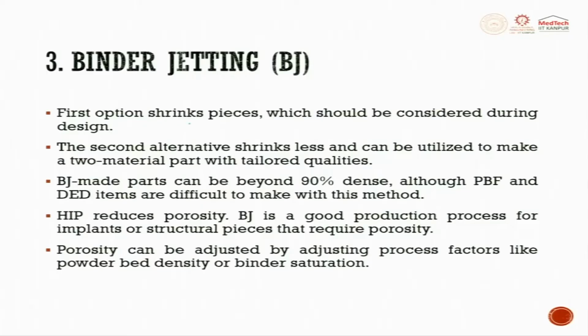The first option shrinks the piece, which should be considered during the design itself, because after this you are going to go for sintering. There is going to be a shrinkage, or a shrinkage allowance has to be given. The second alternative shrinks less and can be utilized to make two-material parts with tailored properties. Binder jet made parts can go beyond 90% densification, although powder bed fusion and DED are difficult to make with this method. HIP reduces the pore size or the porosity.